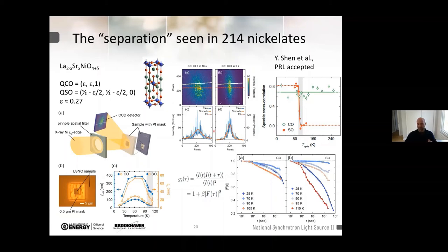We have again speckles. We have the average description and the speckle description. We see that they behave very differently in terms of correlation length, where the spin order is way more correlated than the charge order. However, the dynamic information is also very different and opposite. The one that is mostly correlated changes its time dependence, so the dynamical information, much more drastically than the one that is least correlated. So once again, it seems that the charge order has a memory of what is happening. The spin order can do more or less what it wants under certain conditions, it is more free to evolve, whereas the charge has to come back pretty much in the same condition.